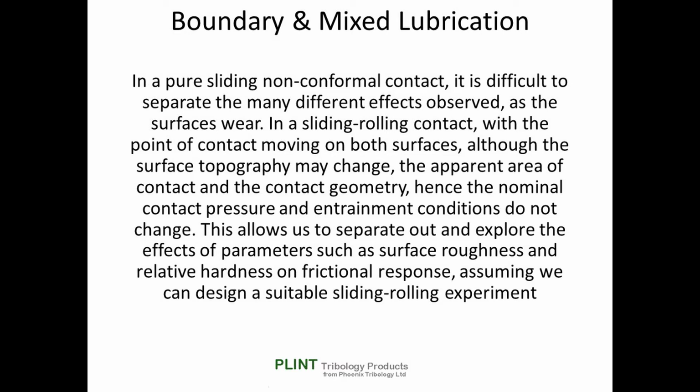In a sliding rolling contact, with the point of contact moving on both surfaces, although the surface topography may change, the apparent area of contact and the contact geometry, hence the entrainment conditions, do not change. If we can design a suitable sliding rolling experiment, we can separate out and explore the effects of parameters such as surface roughness and relative